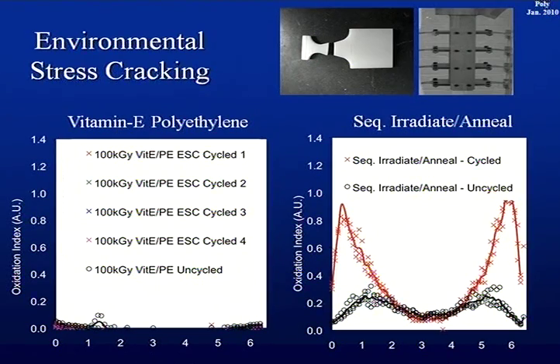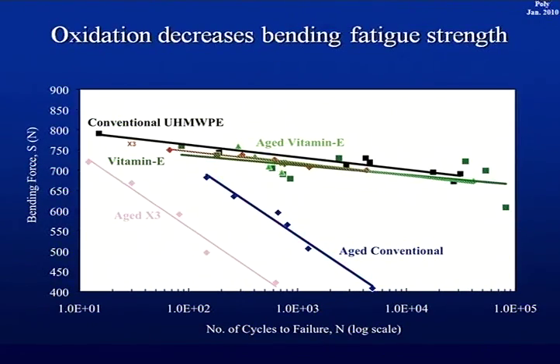If you do what we call environmental stress cracking, where you sequentially load the aged implants, nothing happens to vitamin E. You don't get any oxidation we can measure, at least. But if you do the same with X3 or sequentially irradiated annealed material, it actually fractures. So you can induce oxidation in it, and oxidation decreases the bending fatigue strength. Aged X3 versus normal X3 is up here, aged conventional versus normal conventional, but aged vitamin E and vitamin E, there's really no difference.